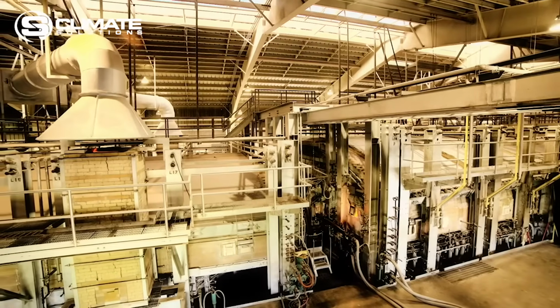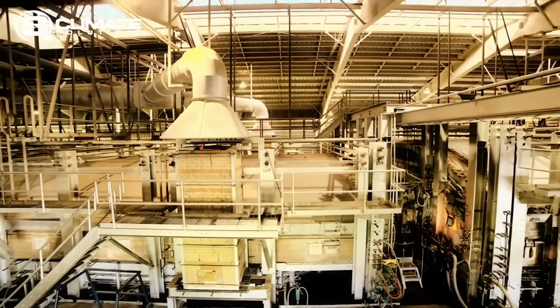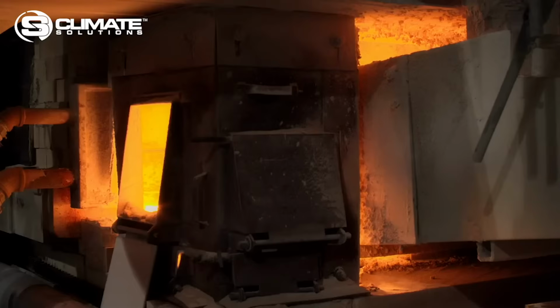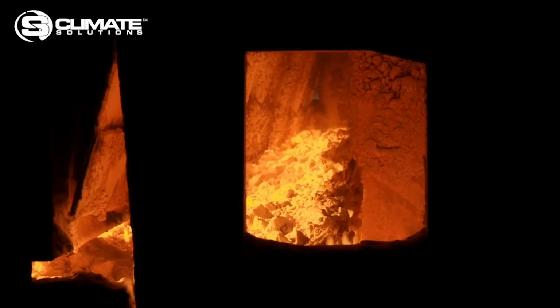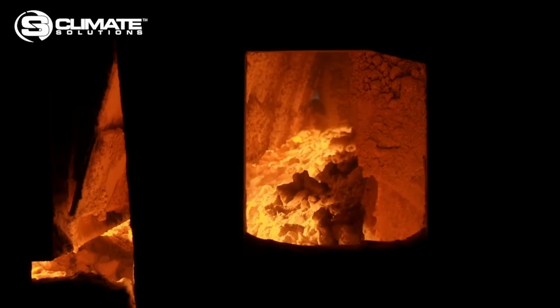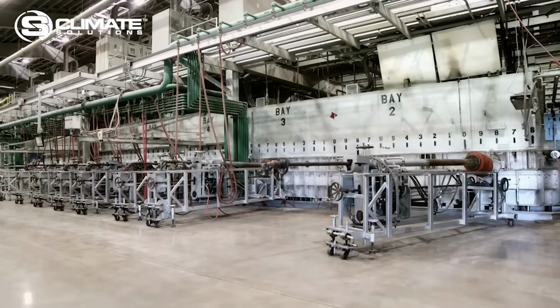The full batch is then conveyed to an enormous 36-foot wide furnace that reaches temperatures of up to 3,000 degrees Fahrenheit. A charger pushes the batch materials into the furnace. The heat transforms these raw materials into a 4-foot deep pool of liquid. The liquefied glass then glides across a molten bath of tin.